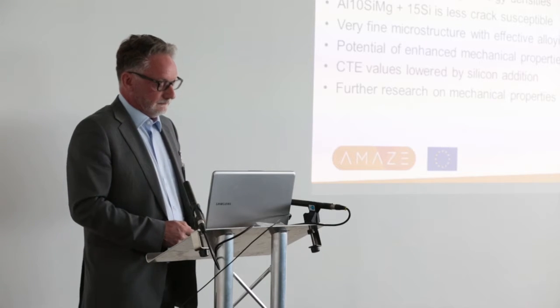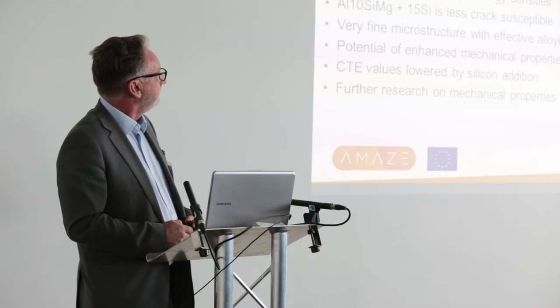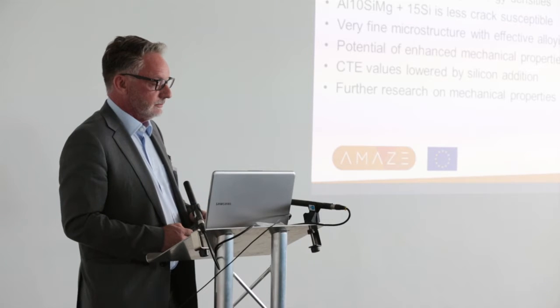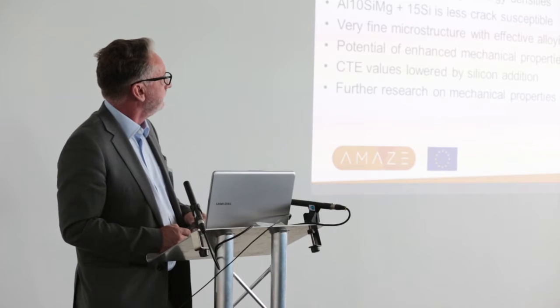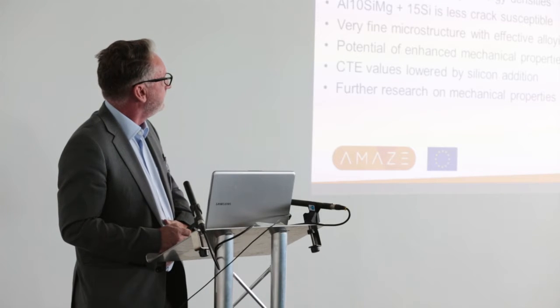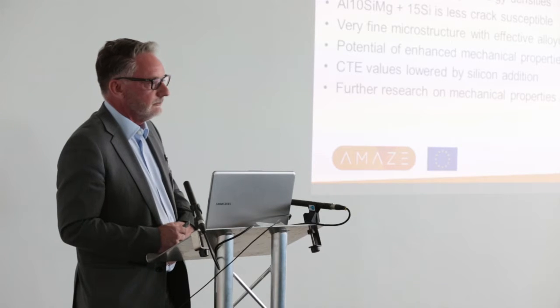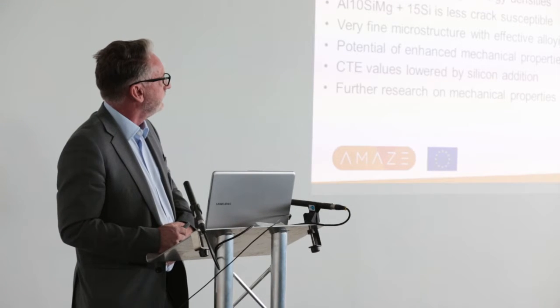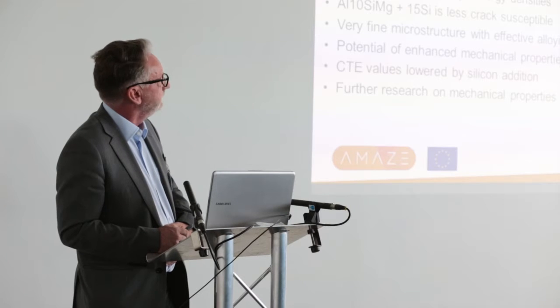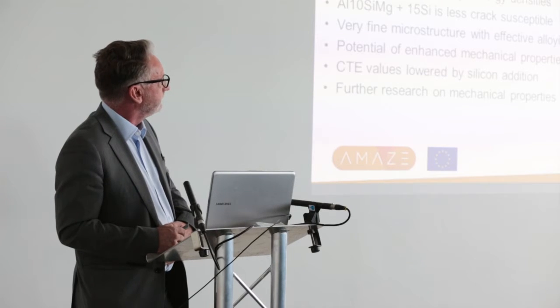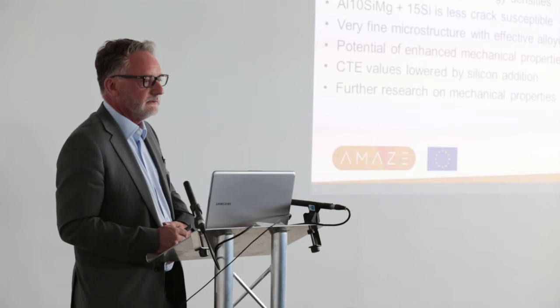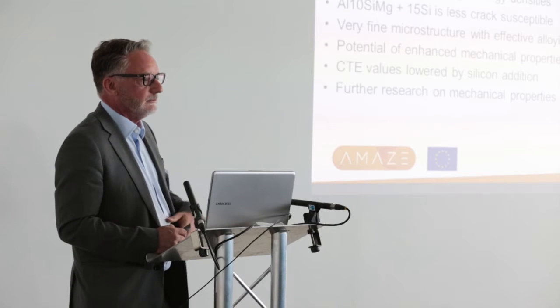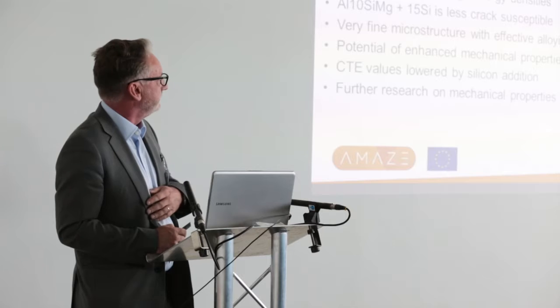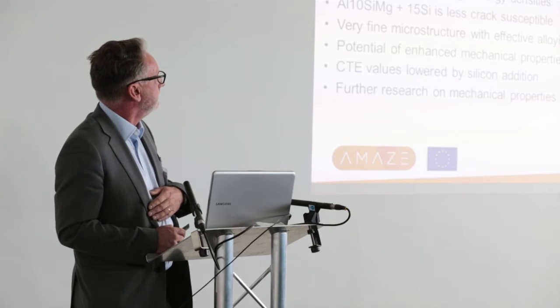So basically, we investigated 3 high silicon alloys. We achieved high density for all the materials. We get some keyhole porosity if we go over in terms of energy density. And we generally found that the aluminium silicon 10 with the added silicon was a lot less crack susceptible than the pre-alloyed material. We get very fine microstructure, and we get effective alloying. On the whole, we avoid the inherited big silicon particles that we've added in, and those have dissolved.